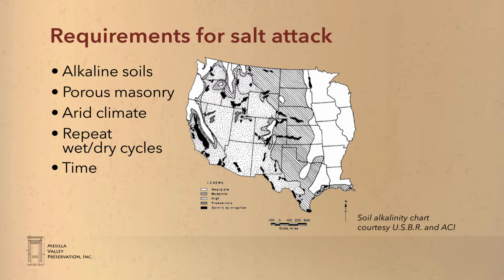Porous masonry is also necessary for salt attack to occur. It is very important to remember that this is not just an adobe problem. All porous masonry is subject to salt attack, including brick, stone, and concrete. Again, the concrete industry is very aware of these problems. In fact, this illustration came from a concrete industry presentation. Although it is counterintuitive, an arid climate is a real driver of salt attack, because dry air drives rapid evaporation that concentrates salts. Salt attack can't exist without evaporation. Of course, the arid West is only becoming more arid these days, as are other parts of the country and world.